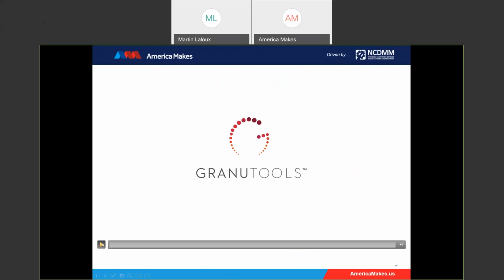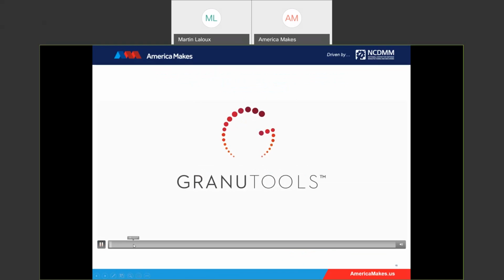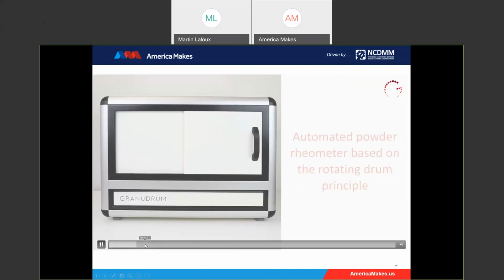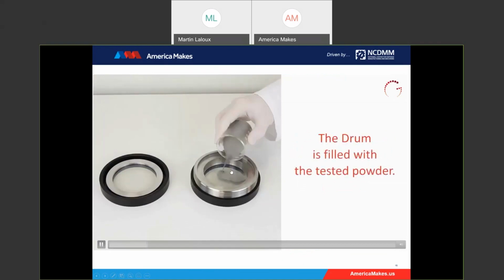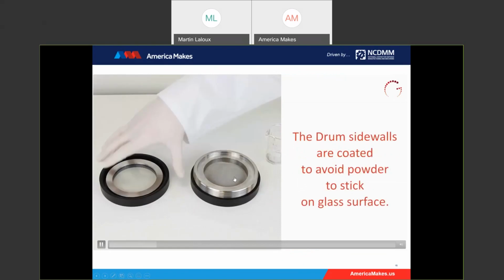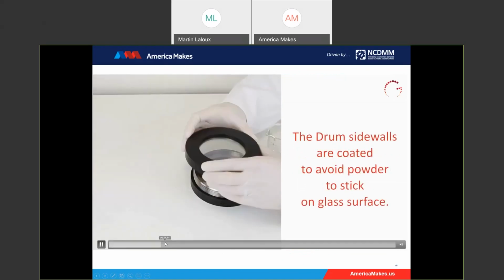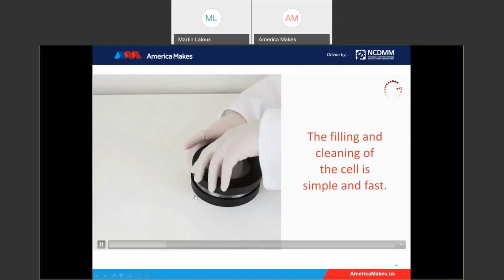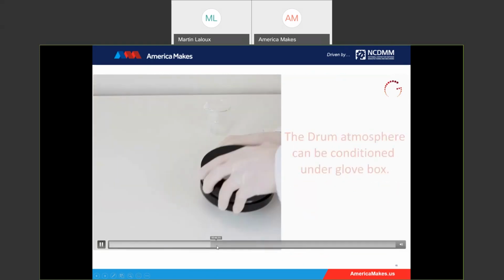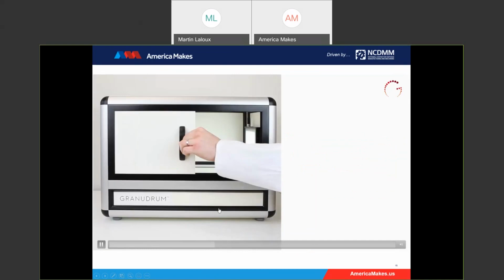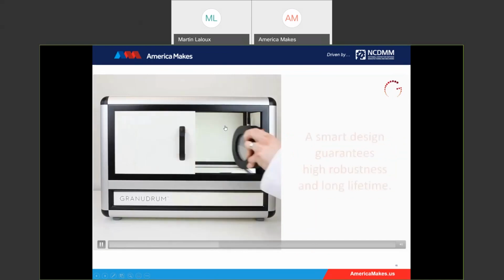To show you the device we use in this study, this is the GranuDrum instrument. This is this box. We pour the powder into this cell, roughly 50 ml, and then we close it up. After that, we measure the virgin powder in this cell, and we can also heat that cell up to 200 degrees. So we put the cell into the machine.